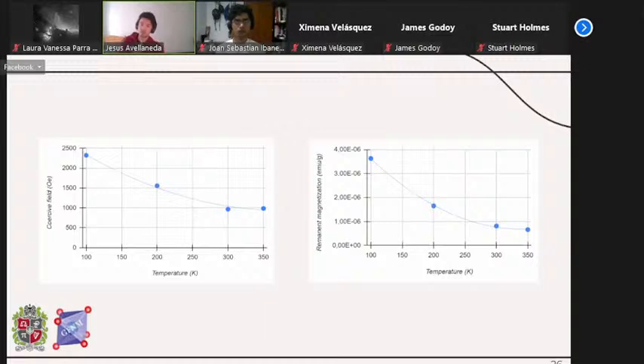As you can see, the fit obtained for both curves confirms that we evidently have a ferromagnetic material, if the hysteresis curves were not enough to realize that. But according to literature, if you have a ferromagnetic material, it should behave like an inverse exponential function. And that's basically what we have here, an exponentially decreasing behavior. So with all those analyses carried out, we can at first glance say that CaLaTiFeO6 places itself in a range of being a subferromagnet.